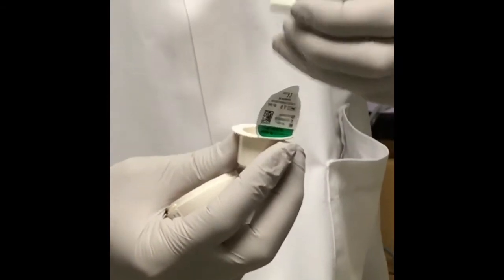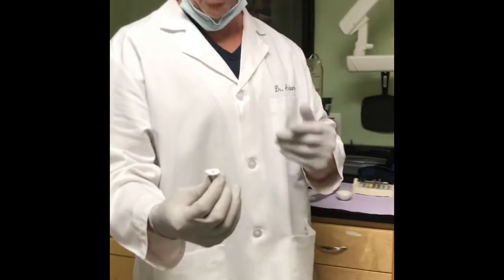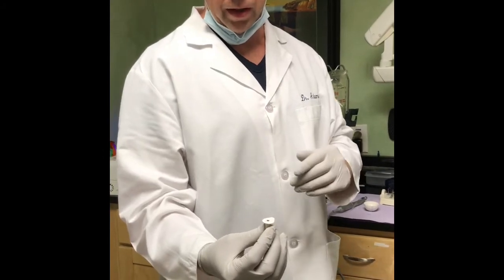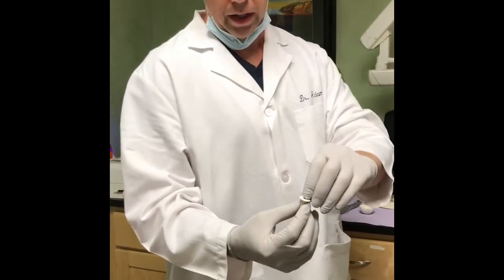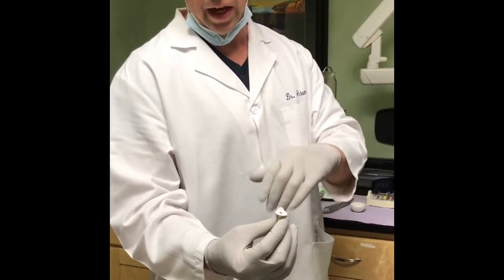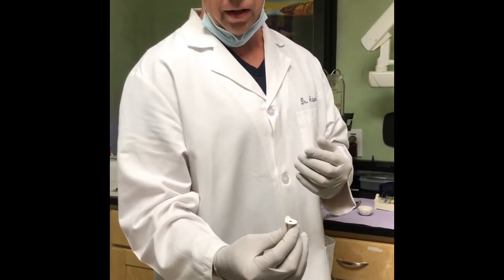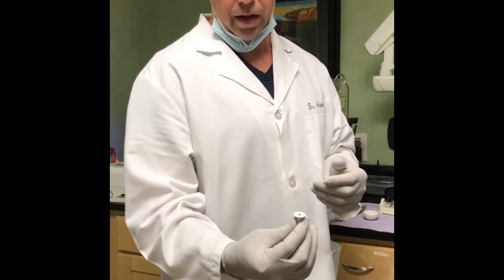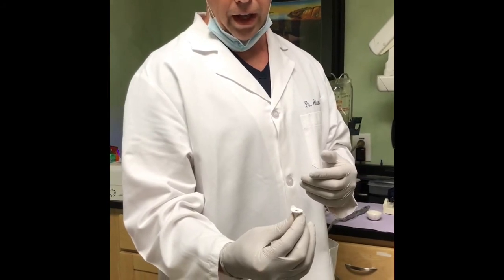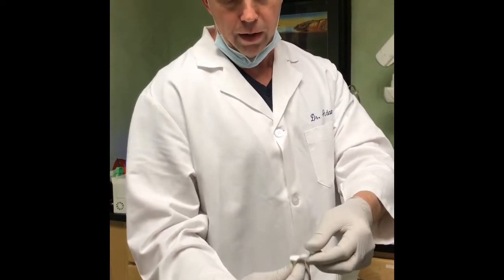I want to talk a little bit about the type of implant this is. It actually appears as a tissue-level implant, not a bone-level implant. However, it's treated almost all the way up to the top — it's sandblasted and etched, and that promotes very, very good bone attachment to the implant. Some of the zirconia implant companies out there do not have the implant sandblasted, and I've seen a lot more failures because of that. So that's one of the things that this implant has really gotten right.